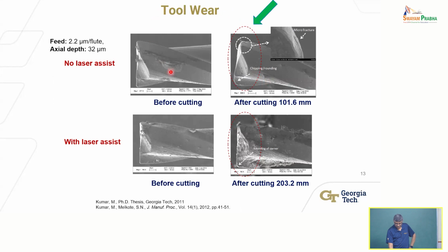Well, this is showing you the condition of the tool. This is without any laser assist, the top row, before cutting. You see some material, this is before cutting, so you can see that the quality of the tool itself from the manufacturer isn't so great. There are some things sticking to the surface. This is essentially an uncoated tool, but this could be dust as well, okay? That could be dust because it shows up in a scanning electron microscope as being very big. But you can see after cutting for about 101 millimeters, there is some rounding of the corners, right? Of the end of the tool. You see that. There is also, if you zoom in this region, you can see there is some microfracturing that has occurred that has led to removal of material, okay?